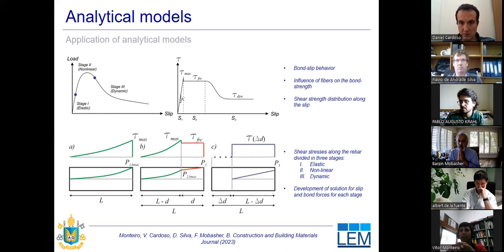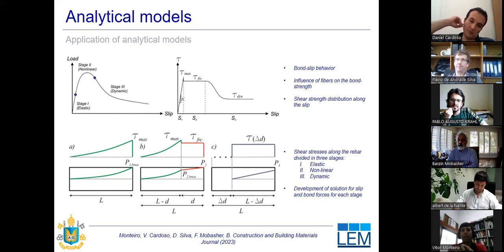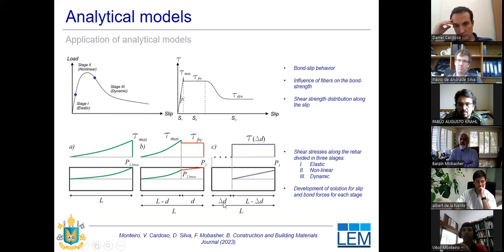So we have the maximum elastic strength, which is presented here after a linear evolution of the strength. Then we have the frictional strength, which is associated with the unbonding of the rebar from the concrete matrix. And after the complete embedment length is unbonded from the concrete, we begin to have the dynamic stage in which the rebar is pulling out from the matrix with an almost constant shear dynamic stress and coming out with this value of delta D, which is the amount of rebar that has already been pulled out from the specimen,